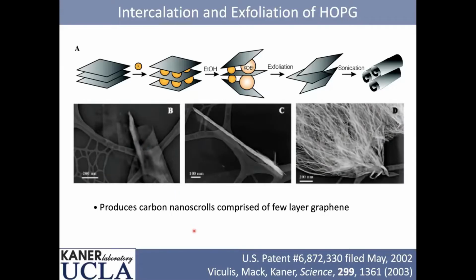Now, what did Novoselov and Geim do? Well, they showed that with Scotch tape, if you keep peeling back and forth, eventually you get to a single layer. What's interesting is, it turns out the Scotch tape is critical, because without the Scotch tape, graphene simply restacks to form graphite, or if it finds itself, it scrolls like this.